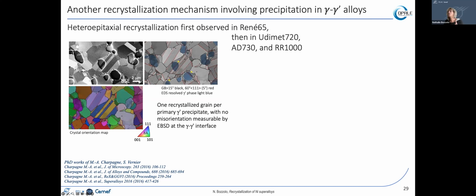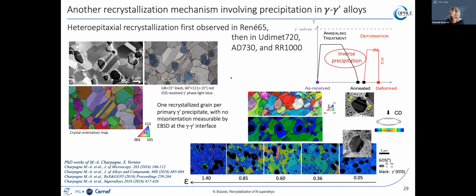Actually, the mechanism which leads to this very particular configuration is the following. Before hot deformation, the material has been heat treated and then slow cooled. In the state reached after holding and slow cooling, we could find at the rim of the gamma prime precipitates some small volumes of another phase, which is actually the matrix phase, or a phase with a composition that is very, very similar to that of the matrix.